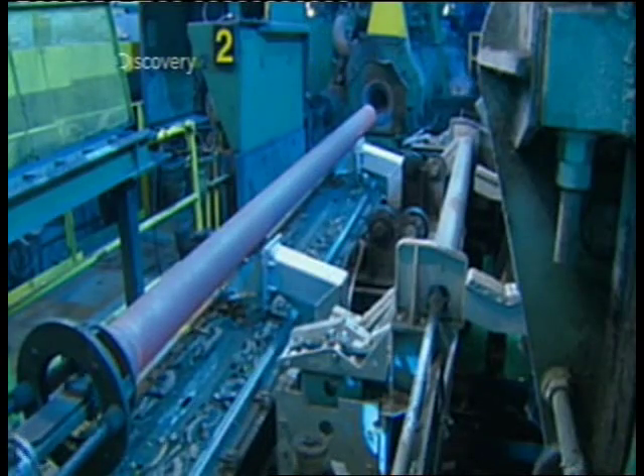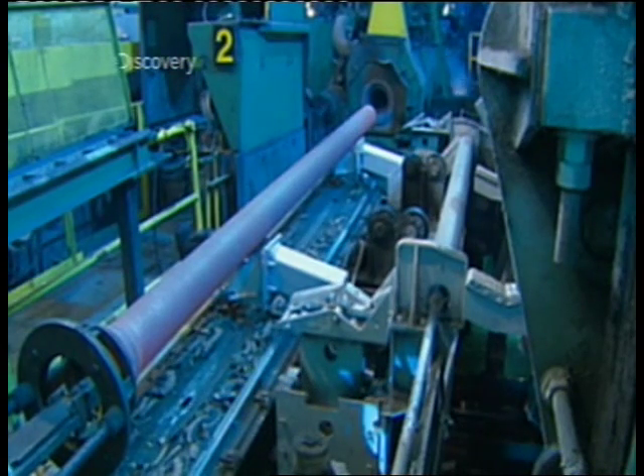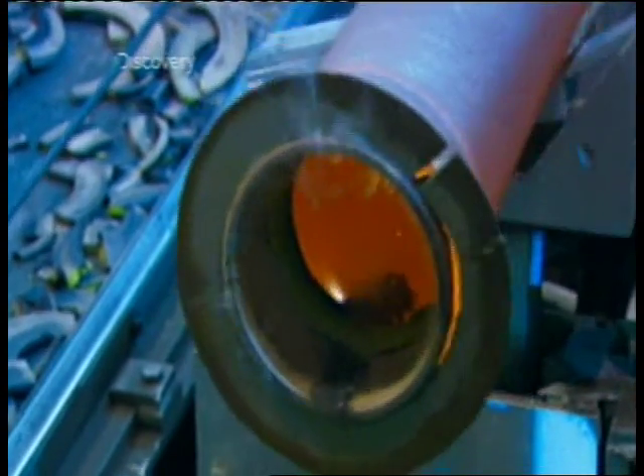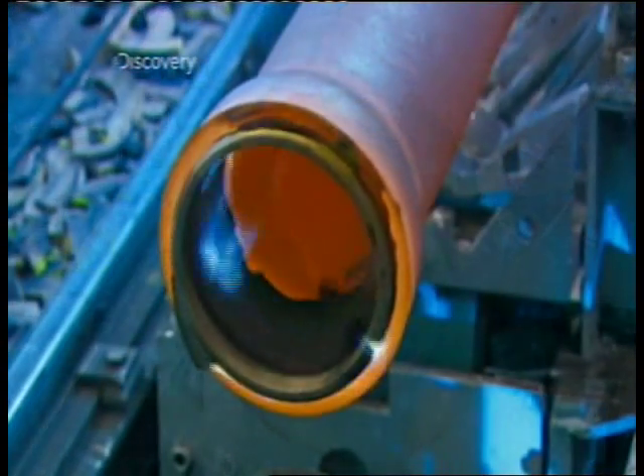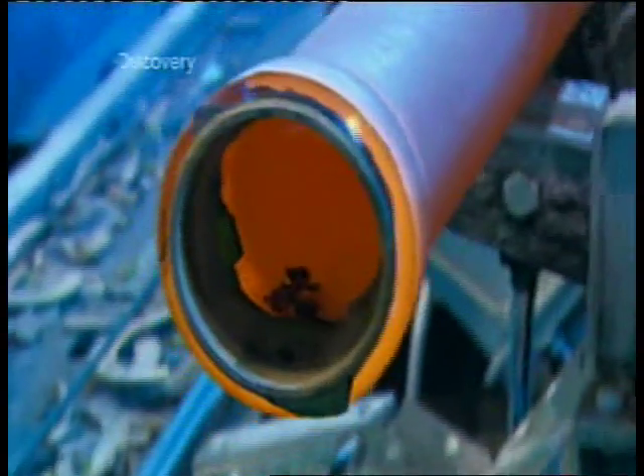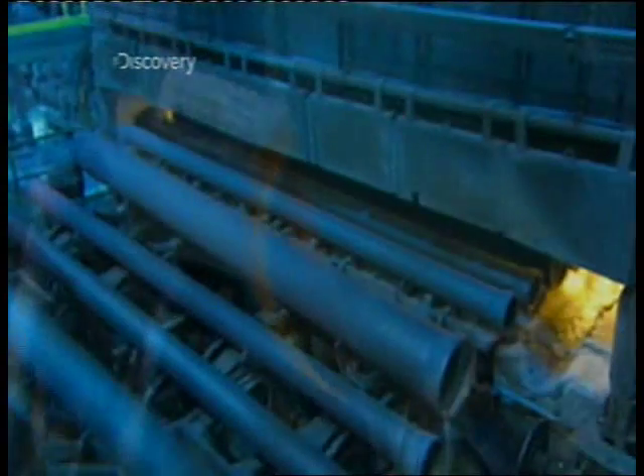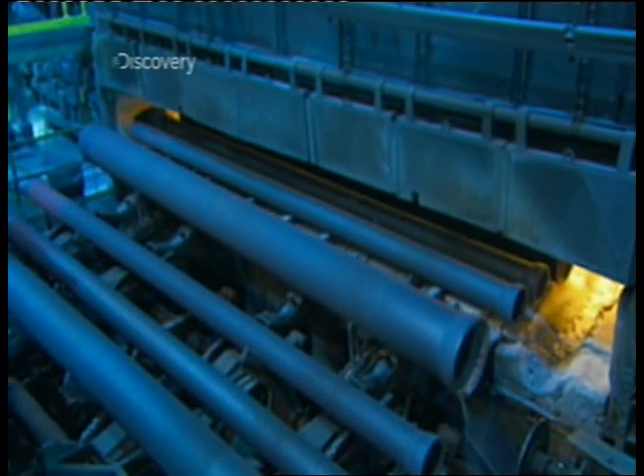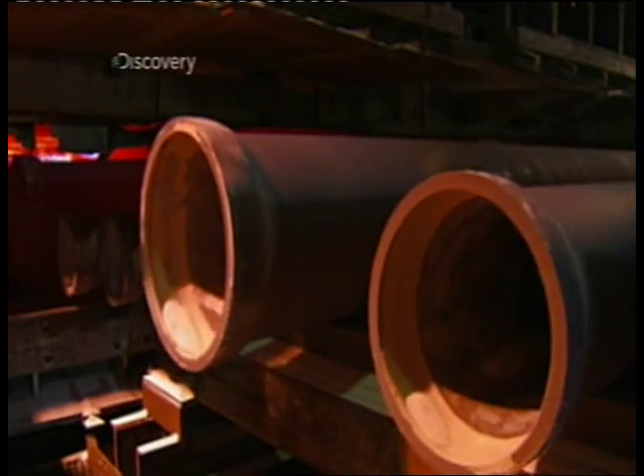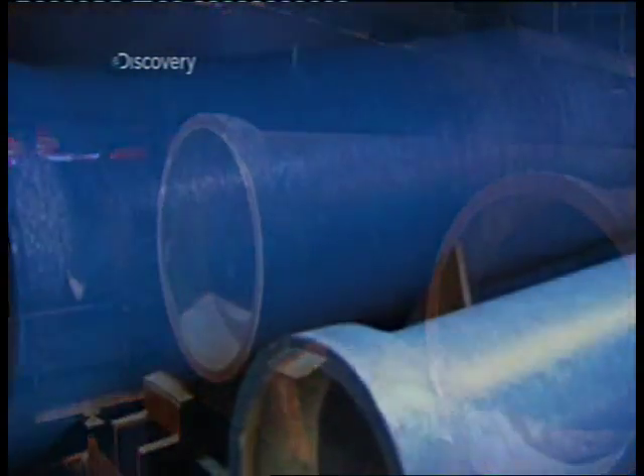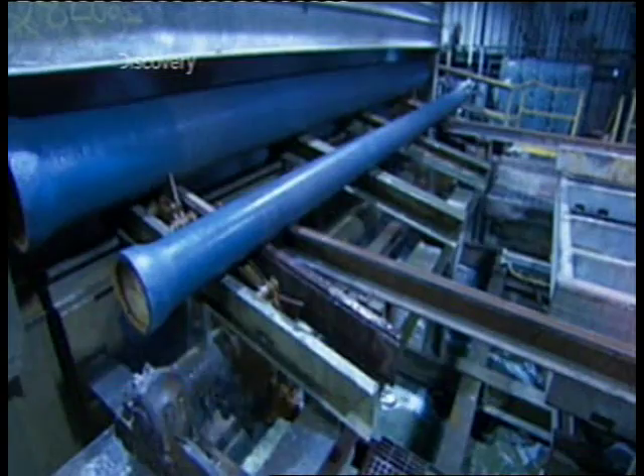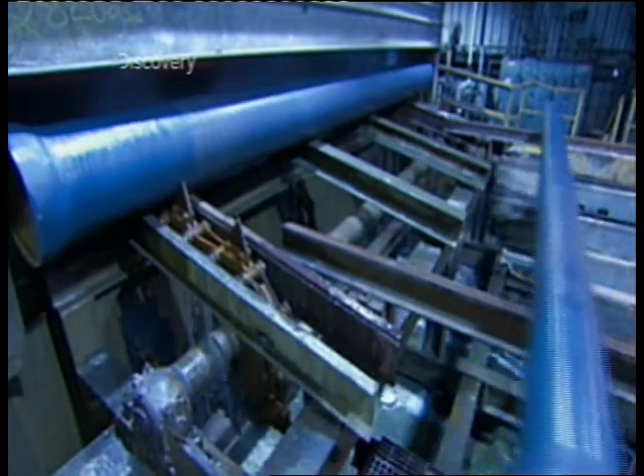A freshly cast pipe is about 800 degrees Celsius, but as soon as it leaves the mould, it cools quickly. Such rapid cooling makes the iron brittle, so the pipe goes directly into a gas-fired annealing furnace that reheats it to 930 degrees Celsius. This alters the internal structure of the iron, making it flexible again. The pipe then runs through a cooling chamber that showers it in cold water.